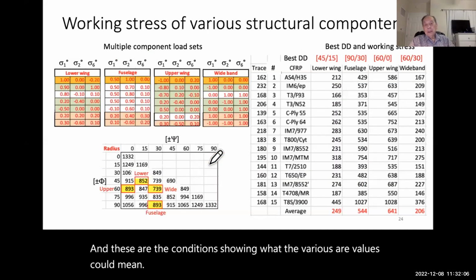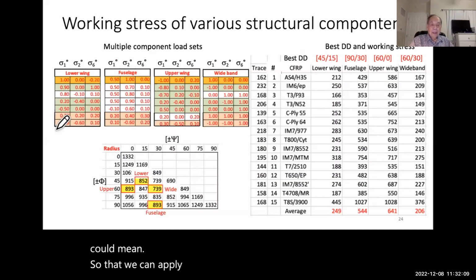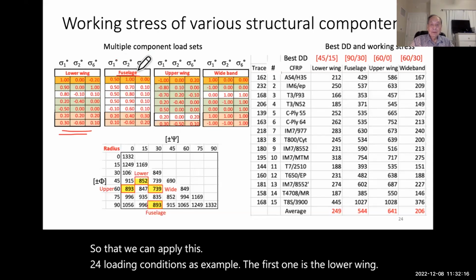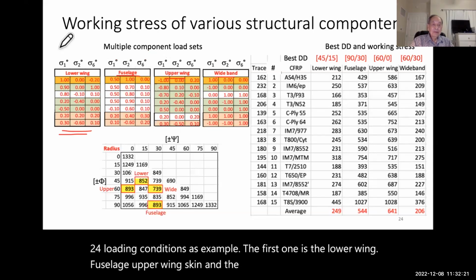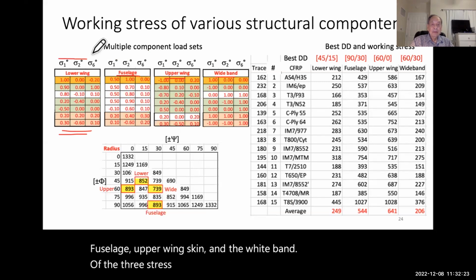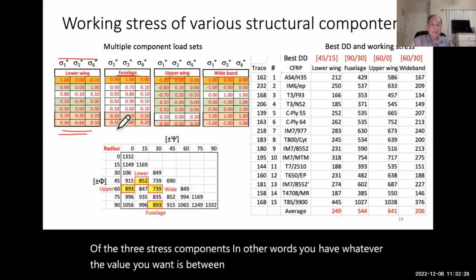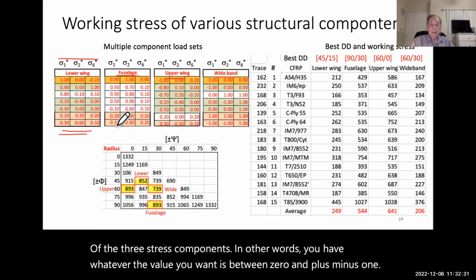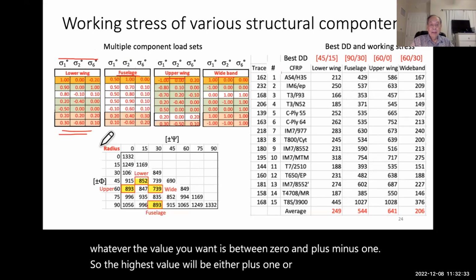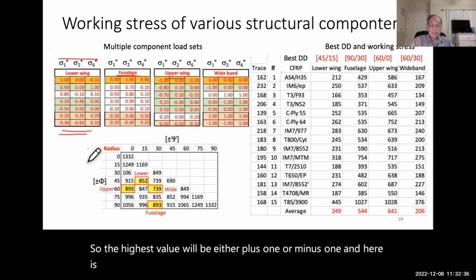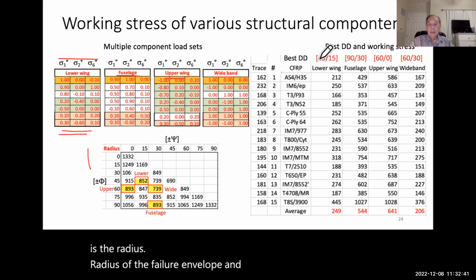So that we can apply this to 4 loading conditions as an example. The first one is the lower wing, fuselage, upper wing skin, and the wideband. Of the 3 stress components, you have whatever the value you want, between 0 and plus or minus 1. So the highest value will be either plus 1 or minus 1. And here is the radius of the failure envelope, so that you find what is the best laminate.